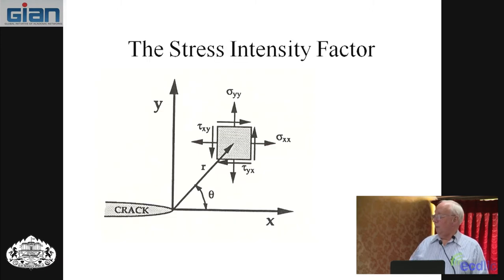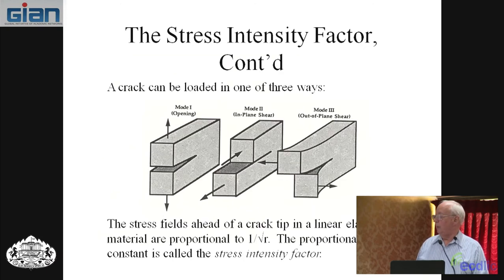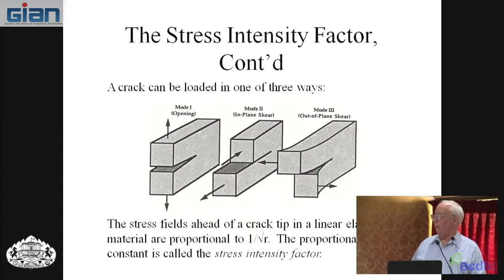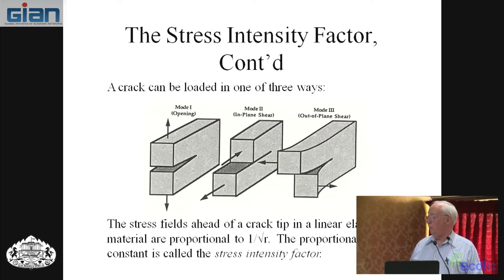Now, the Irwin approach is a stress intensity factor approach based on stress rather than energy. And he showed that if you have a cracked tip and look at the stresses around the cracked tip, and this is two-dimensional, x direction, y direction, normal stresses, and then shear stress, tau xy, that element then is at a distance r from the crack tip and at some angle theta from the horizontal. So those terms all come into his stress analysis terms. Now, before you look at them, have to talk about the modes of loading. There are three modes of loading.